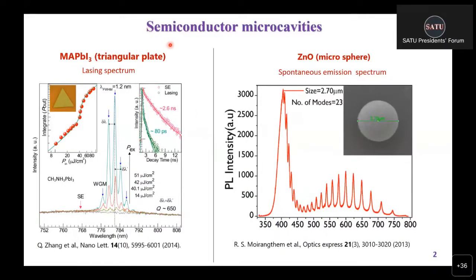Okay, semiconductor microcavities. When researchers fabricate semiconductors, they can usually observe some microstructures. In the left figure, the material used is MAPbI3, a kind of perovskite, and the microstructure shown here is a triangular plate. This microstructure constructs a microcavity that can confine optical photons very efficiently. When the external pumping is above the lasing threshold, we can observe multimode lasing behaviors in the spectrum.